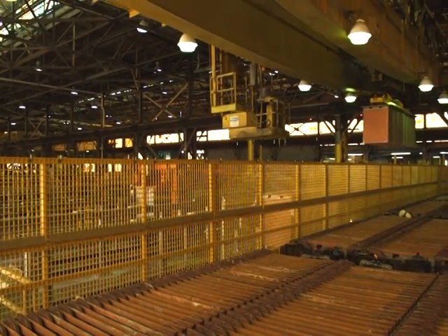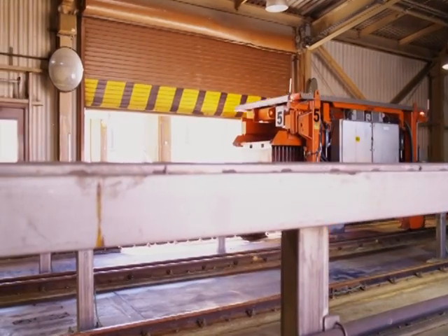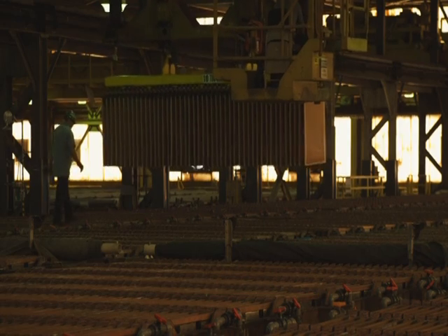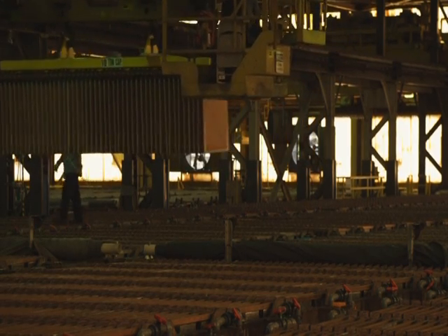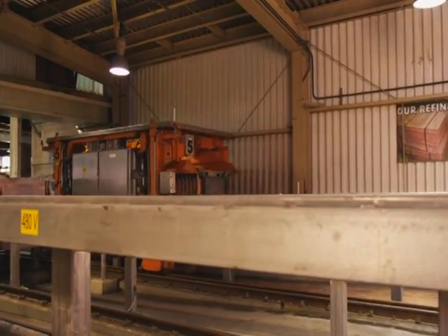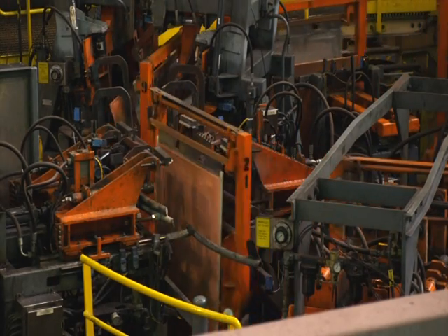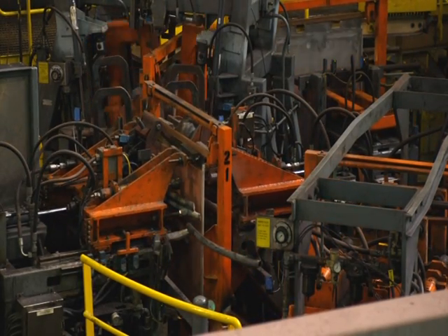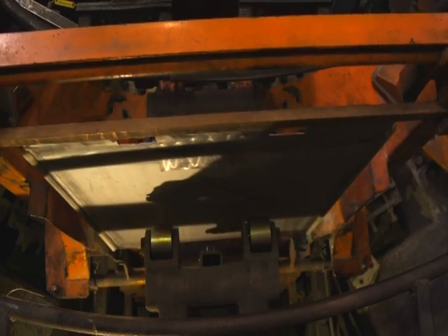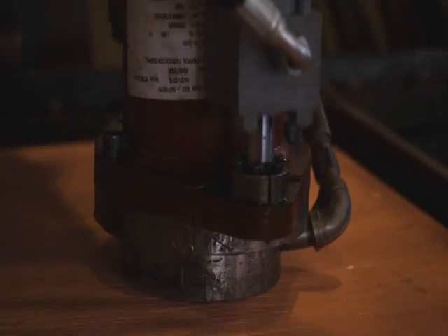After 10 days, the refining process is completed, and the 300-pound copper cathodes are removed from the cells and placed on racks. The transport cars then carry the product back to the material preparation center. Cathodes and stainless steel blanks, along with scrap anodes, are washed to remove any residual electrolytes and slimes, which are pumped back to the tank house and then to the precious metals plant to recover byproducts that include gold and silver. Cathodes are processed through two cathode stripping machines, where the copper cathodes are separated from the blanks. The blanks will be returned to the tank house for another refining cycle. After being stripped from the blanks, the 99.99% pure cathodes ride a conveyor, where they are sampled and analyzed for purity.